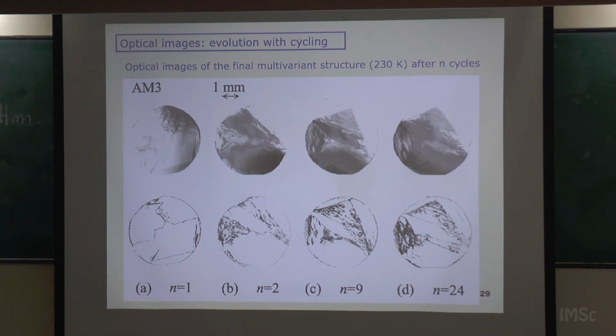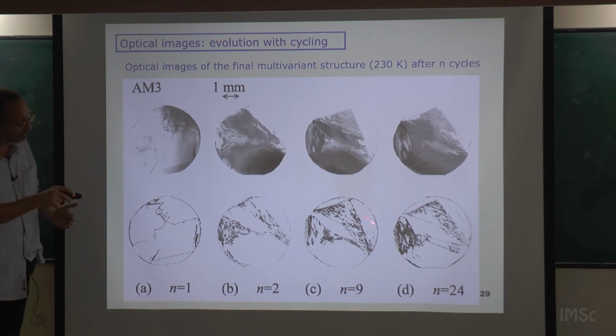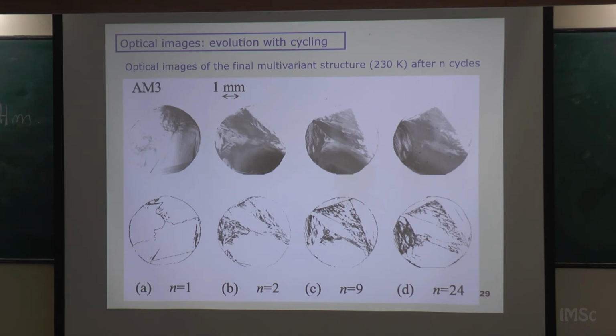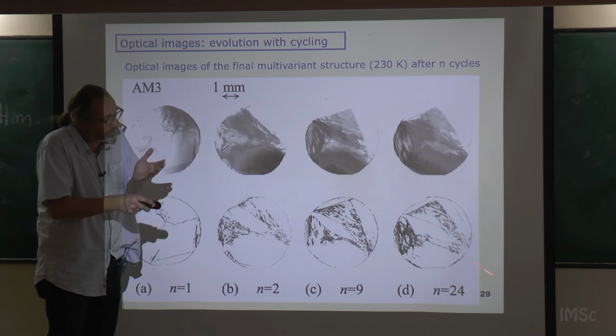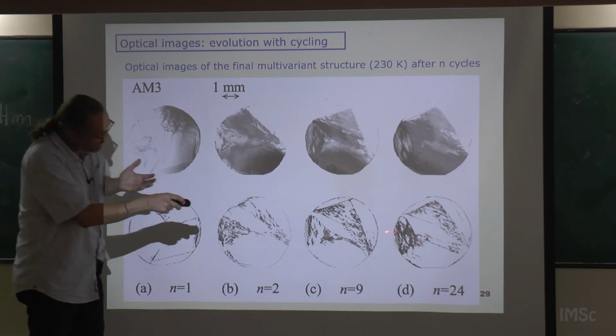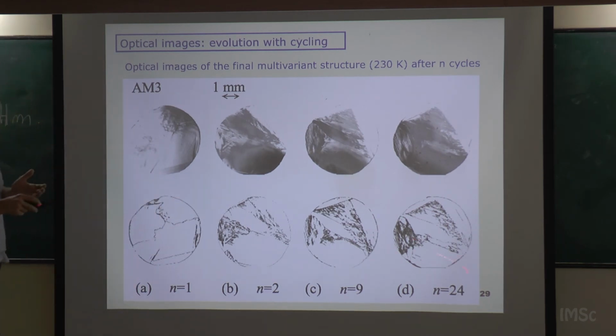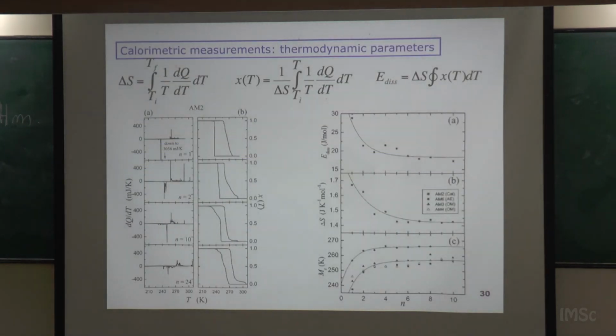So the picture I showed you was of this kind. It had many, many different domains. But this picture is not obtained the first time you cross the transition. You have to cycle it many times, and then at the end you get a sort of stable pattern. In some cases, there are still big domains, but there are many small ones. And what we wanted to measure in this work is to check whether this somehow reaches a limiting structure, a limiting preferred distribution of domains, okay?